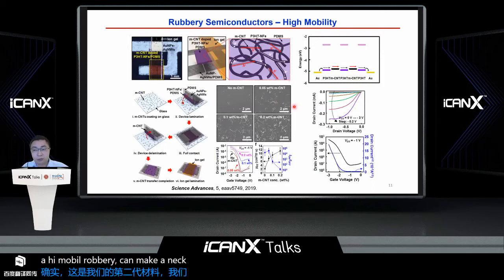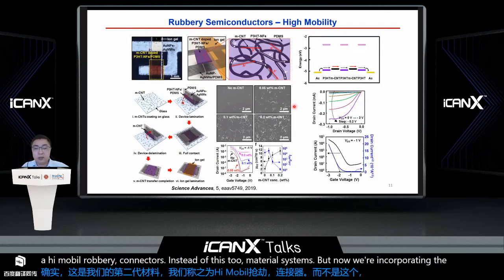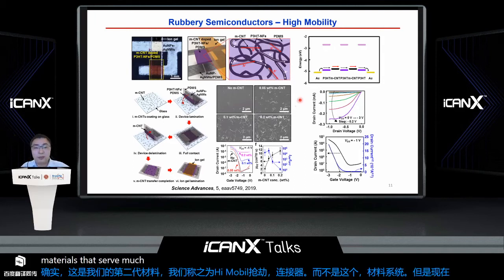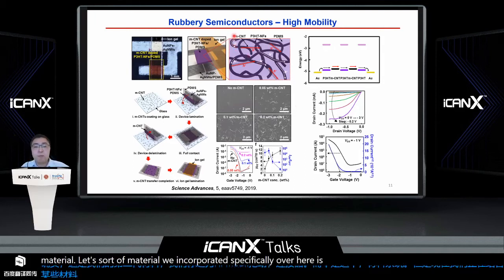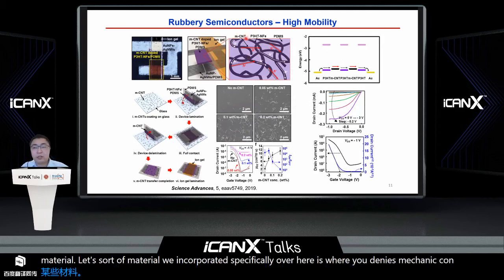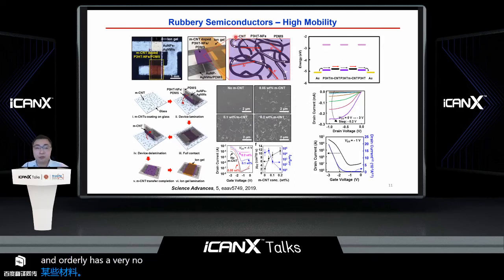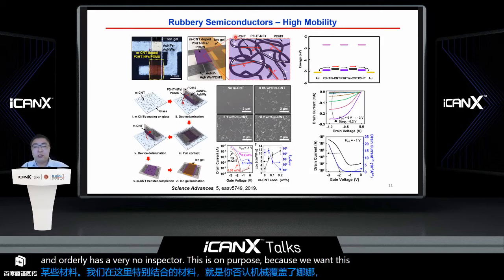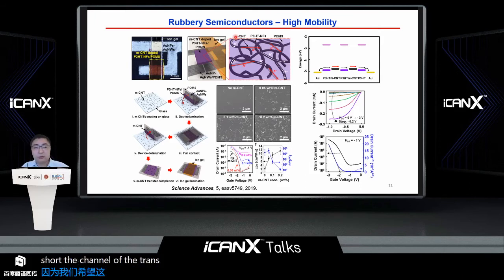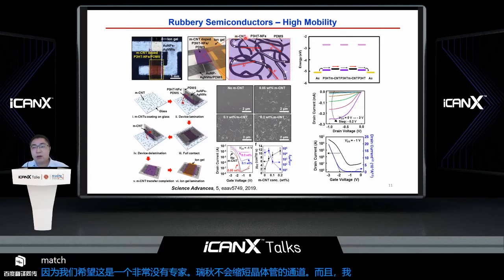Instead of this two material system, we are now incorporating a third material. The third material we incorporated is metallic carbon nanotube, which has a very low aspect ratio. This is on purpose because a very low aspect ratio does not short the channel of the transistors. We also utilize this metallic carbon nanotube because the work function matches very well with the HOMO level of the P3HT nanofiber, allowing the carrier to flow through easily.